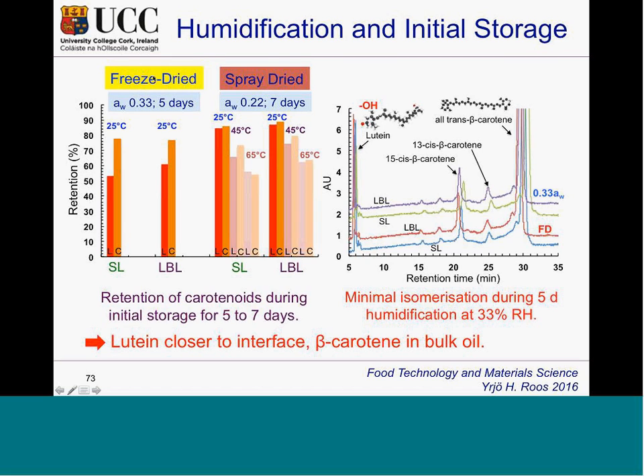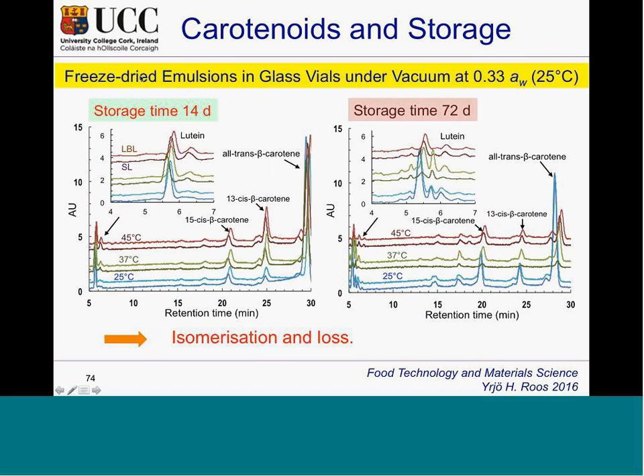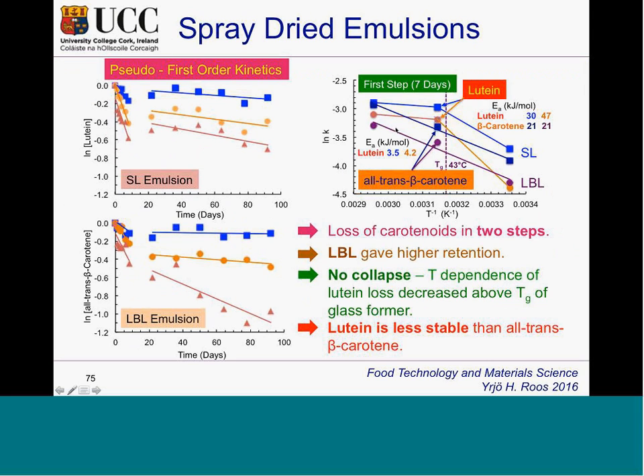We can see that there are two steps. First, especially in spray-dried materials, there is a rapid loss, because there's always some air occluded in the material, the air in the particles that's consumed, and that causes a rapid loss, and then a less rapid loss, so two different kinetic phenomena. Single layer emulsions, so one single layer of whey protein, are typically less stable than the multilayer emulsions. So not only the glass properties are defining the stability in processing and storage, but also the way one defines the interfaces has to play a role.